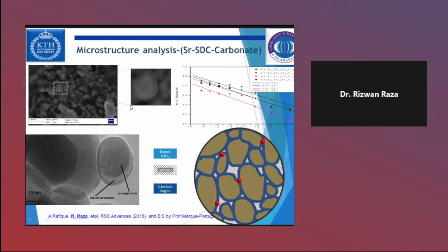So another work regarding that, from this nanocomposite, one of my PhD students developed one more material, but she has seen that co-doping effect. Before it was samarium doped ceria (SDC), but after that we have introduced the co-dopant strontium, and there is again a coating with the carbonate, and you can see from this TEM image and this SEM image, there is this like a core shell. So it can be animated like this, and it can be seen this way.